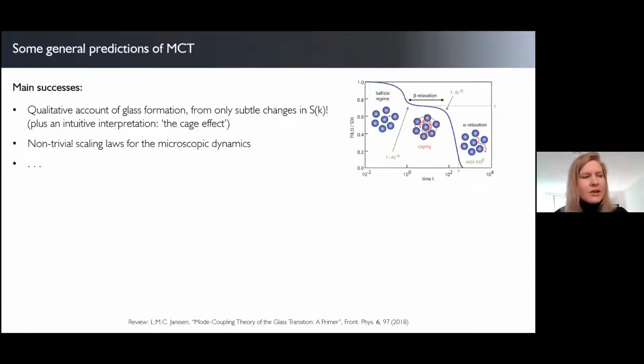And so by now, the theory has been around for quite some decades. And by now we know there are some things the theory can do really well and some things it cannot do so well. So one of the main successes is that it gives a qualitative account of glass formation, taking only the static structure factor as input and looking at these tiny, tiny changes in the static structure factor. Somehow the theory is able to predict indeed the emergence of glassy behavior in a glass transition from only those tiny structural changes. So that's really a remarkable success of the theory.